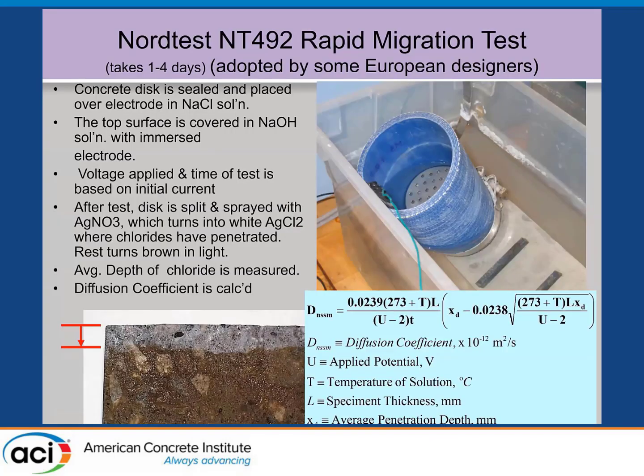The other one that has been used, and I know one of the consultants used it on that recent bridge that was built in New York, across the New York Harbor, was this test method, the rapid migration test. In a lot of respects, it looks like C1202. You've got a sodium chloride solution on one side, sodium hydroxide on the other. You apply a voltage. But in this case, instead of putting 60 volts in, you measure the initial current flow through the concrete and you pick the voltage and the time of test based on that, because at the end of the test you split the cylinder disc open and you spray it with silver nitrate, and it turns white if it's where the chloride has penetrated, as it turns to silver chloride.